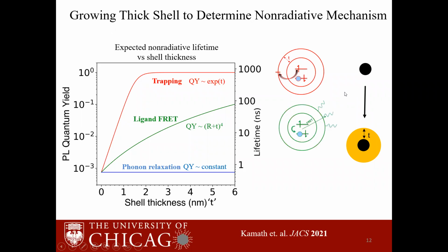The second mechanism, which is FRET to ligands, involves a fourth power dependence on the distance of the quantum dots from the ligand shell. So as we grow this thick shell, we should expect the quantum yield to increase as a fourth power of the total nanoparticle radius. And the third mechanism is multiphonon relaxation. And this is something that is intrinsic to the core. So even if we grow a shell, it will not do anything to change the phonon relaxation rate. So we should expect the quantum yield to be independent of the shell thickness.